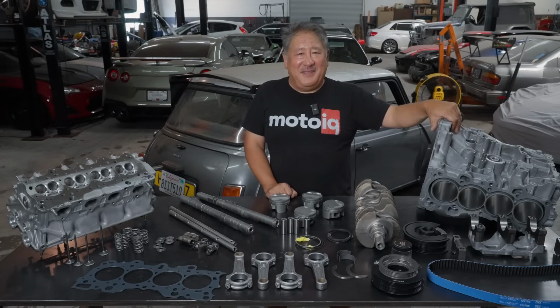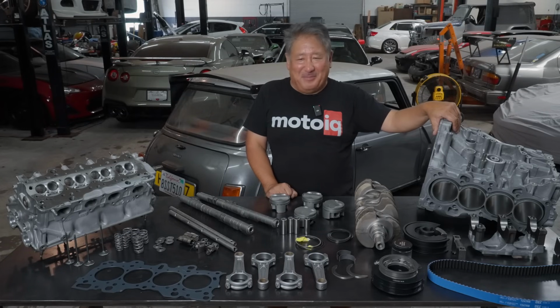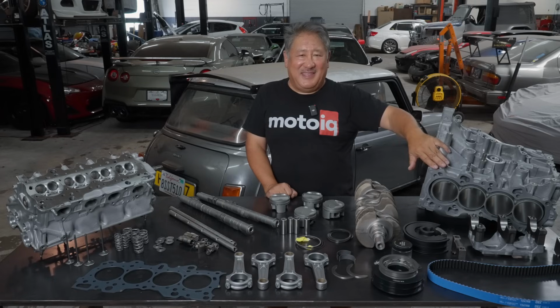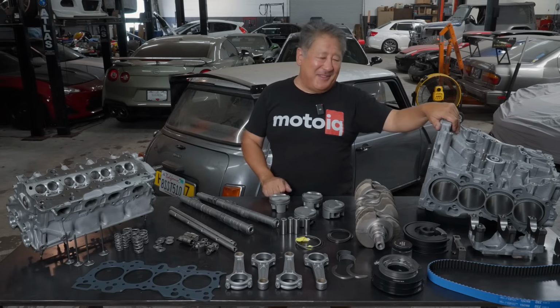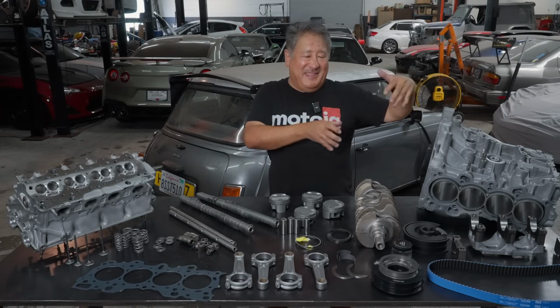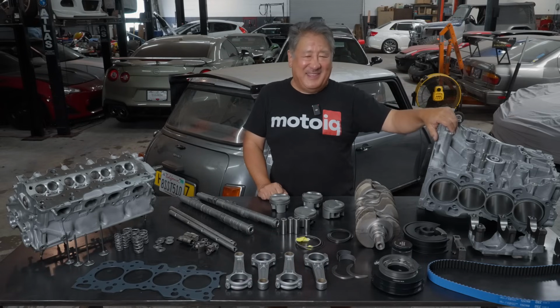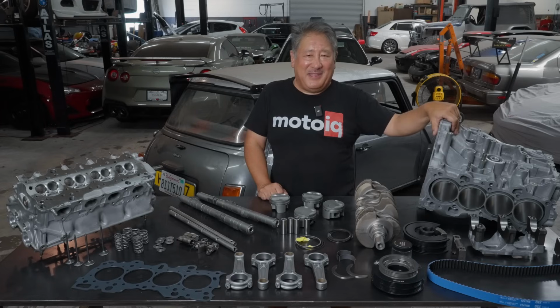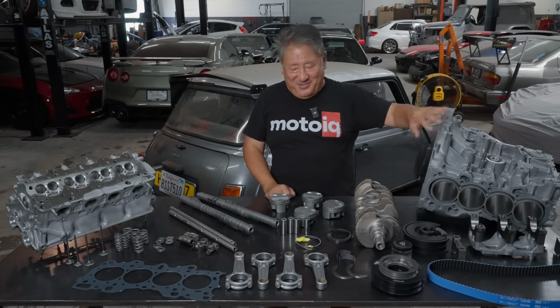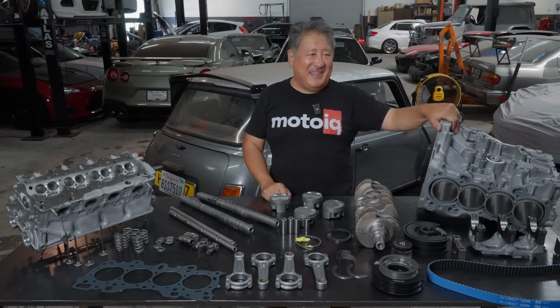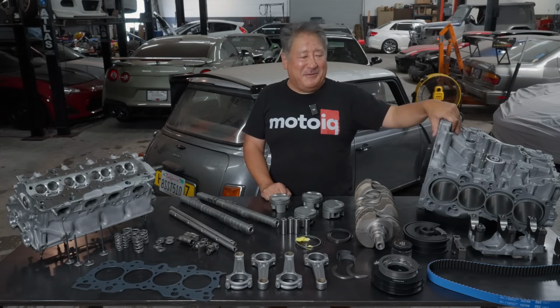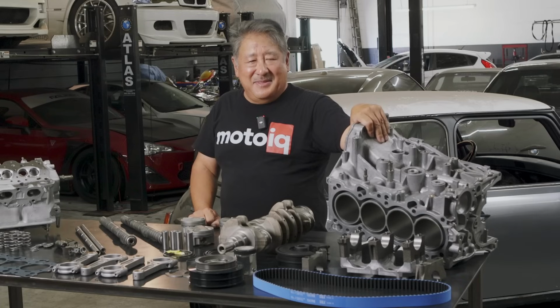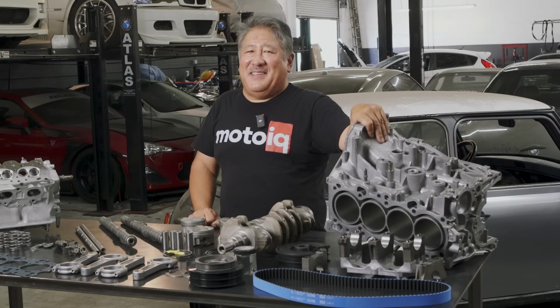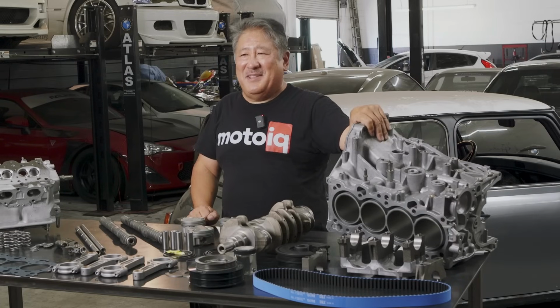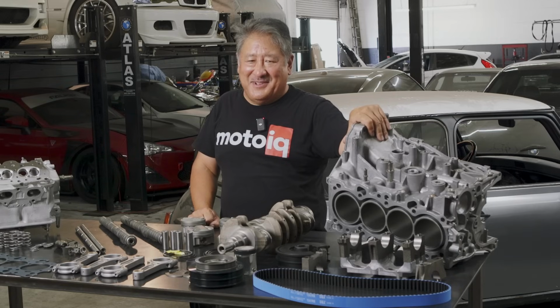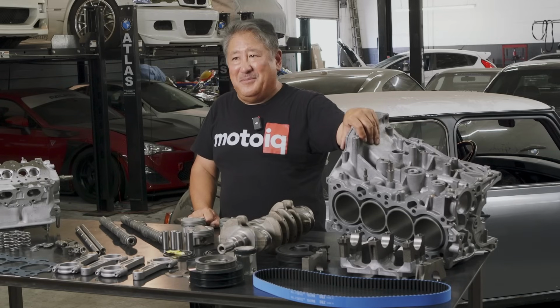We used a torque plate. A torque plate is a big stiff metal plate with holes in it that simulates the torque of having a cylinder head bolted down. So it distorts the block in a similar way to installing the head. You do all your machining with the torque plate in place and let all the distortion occur. That way when you torque down your head, your cylinder wall is perfectly round. Now, this isn't absolutely critical on the Honda engine. On some engines it's mandatory because they distort so much, but these don't distort too bad.